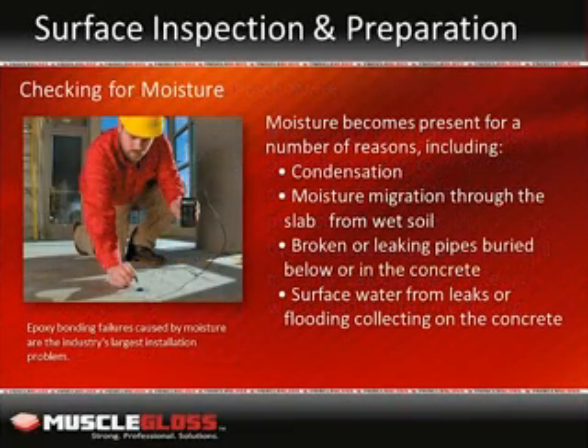Checking for moisture. Moisture becomes present within concrete surfaces for a number of reasons, including condensation, moisture migration through the slab from wet soil, broken or leaking pipes buried below or in the concrete, and surface water from leaks or flooding collecting on the concrete. Epoxy bonding failures caused by moisture are the industry's largest installation problem. MuscleGloss recommends testing for moisture transmission as part of the inspection process. The recognized methods are